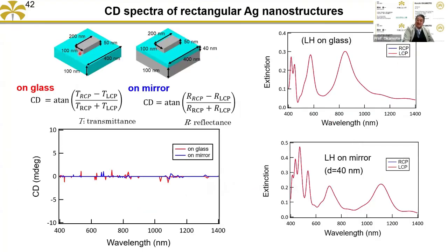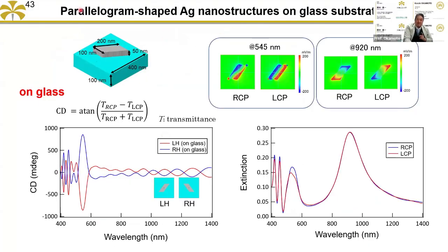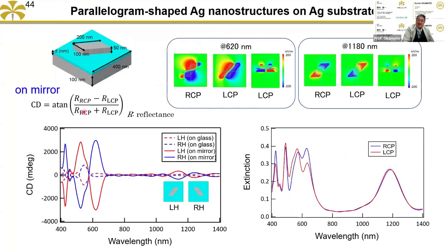Using that, first, this one is symmetric, just a rectangle. In that case, left circular polarization and right circular polarization are almost the same, and there is no CD. But if it's a parallelogram, it's an asymmetric structure. So for right circle and left circle, the electric field distribution is different, the extinction is different, and the CD is generated. On the graph, the CD has one peak with this intensity. If we put that on the metal substrate, it increases three times larger, and there are also more peaks. That's why we found that using this structure, we can enhance the CD spectra.